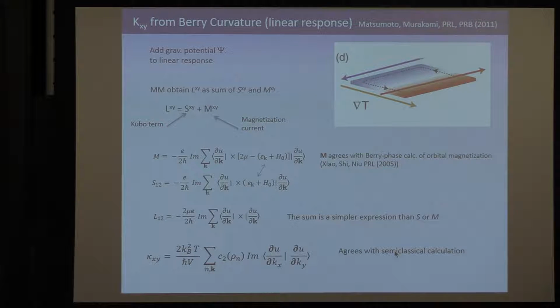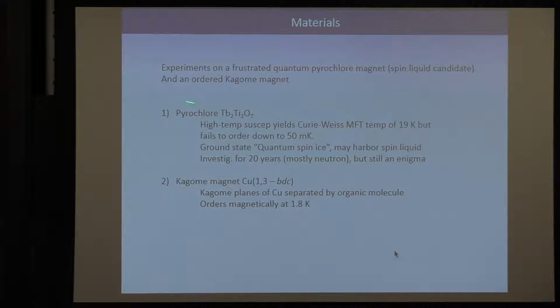Right? Okay, anyway. So the two materials are the pyrochlore, terbium titanate. To answer the previous question, this has a high temperature Curie-Weiss susceptibility that predicts a Curie-Weiss temperature of 19 Kelvin. So it should have ordered, plus or minus a factor of 2 at this temperature. But folks have cooled it down to 50 millikelvin and nothing happens. So it's in zero field. Once you apply a field, you spoil the frustration and it orders. So this is sort of a leading candidate. And some people call this the quantum spin ice.